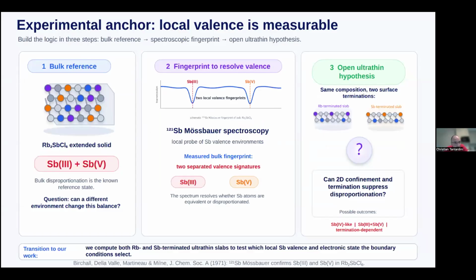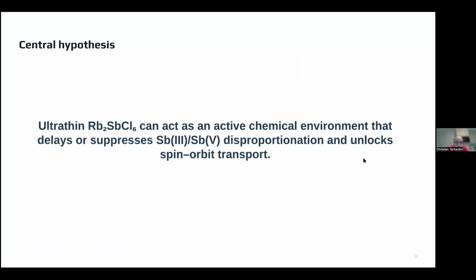About why we are looking at antimony, we know very well that there is this Mössbauer experiment that confirmed that at the moment what people see for the bulk is antimony-3 and disproportionation. So actually we have antimony-3 and antimony-5 for our rubidium 2 antimony chlorine 6. So what we want to see is if we can make a rubidium terminated slab and an antimony terminated slab, and see if this confinement can make a different outcome. So this is the central hypothesis that we would like to confirm today.